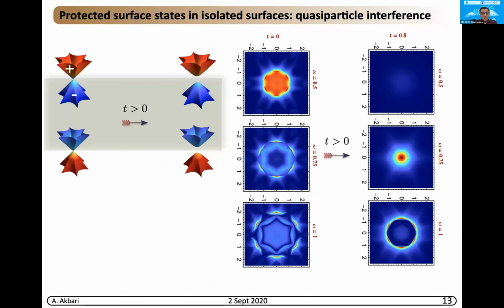We can just run the calculations and look at what we can learn from the quasi-particle interference pattern. On the left-hand side, we have the quasi-particle interference pattern for zero hopping, and you see that it starts from some kind of drop-like isotropic feature at low energies, and by going to higher energy it starts to show some snowflake feature, and this snowflake feature becomes wider and wider by going to higher energy. This is exactly what we expect, which we also saw in the typical topological insulator.